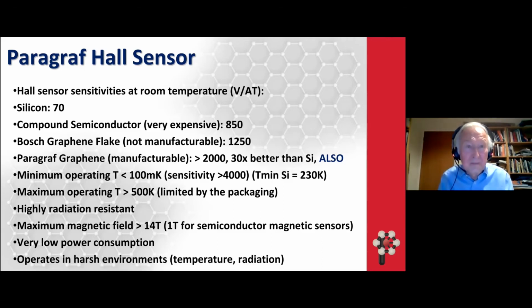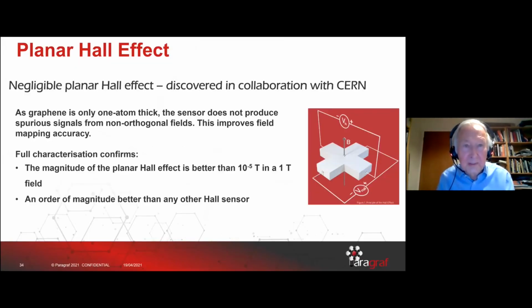So this is the planar Hall effect, which I'd not heard of. We have a collaboration with CERN, and this was discovered while we were working with CERN on our Paragraf Hall sensor. The planar Hall effect arises because if you have a normal Hall sensor, which has a finite thickness, then you get spurious signals from magnetic fields which are not orthogonal to the sensor. So that reduces the accuracy.